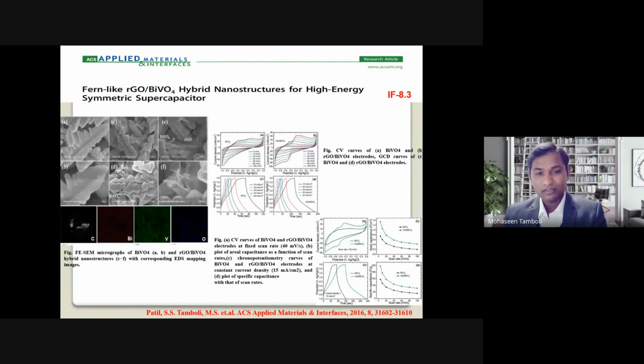Then we checked this material for supercapacitor applications, and considering the electrical properties, it also shows a good specific capacitance, and it has almost more than 90% retention capacity for the optimized reduced graphene oxide BiVO4 composites.